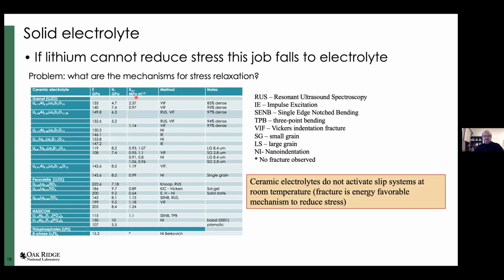In simple words, it's a resistance of material to propagate an existing crack. And if you look at all these values compiled for different garnets and perovskites and NASICONs, they're generally at around 1 megapascal square root per meter, which is very, very low. The same fracture toughness for the metallic materials would be 20 megapascal square root per meter. So this is an orders of magnitude difference, and it's not a big surprise.